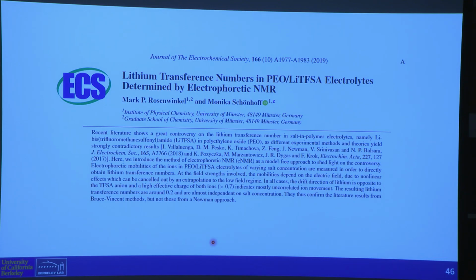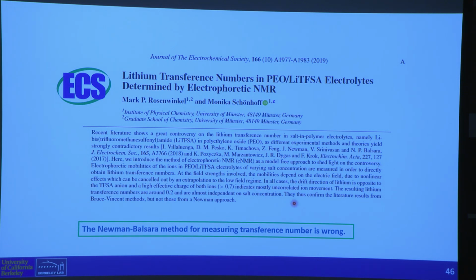Here's a paper where our paper is part of this, in the abstract, essentially saying that our method is wrong and our measurements are wrong and our interpretation is wrong. Everything is wrong. For example, they say, in all cases, the drift of lithium is opposite, and it indicates mostly uncorrelated ion motion. If you have uncorrelated ion motion, t plus 0 should be positive.